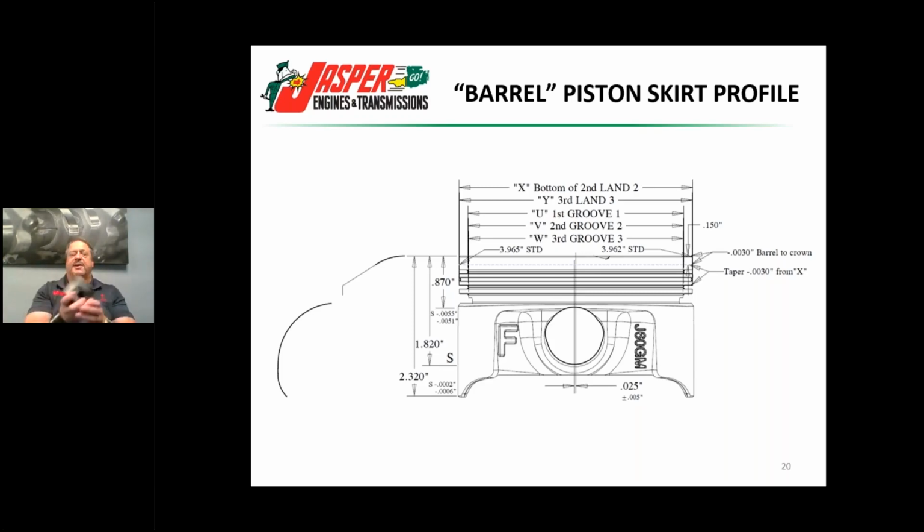Many times in some of the old engines that you would tear down, you could see that, where you would see part of the top of the ring lands here is more scuffed than anywhere else. Our deal is we want to make sure, since we have CNC capability and can put anything anywhere, that we actually draw that in. So once it reaches optimum temperature, it draws itself out, because the heat is going to be so much in the crown and the lands, it's going to expand further. So when you get this and you get the wear patterns down, then you've got a really nice piston to be able to be stable. The deal is to make sure the piston is stable, so the rings are square in the bore and seal better and reduce blow by.